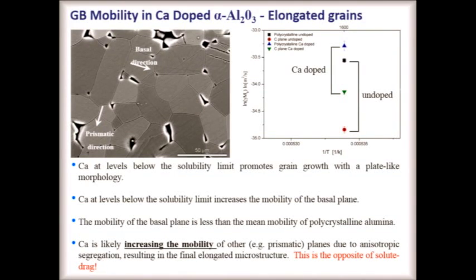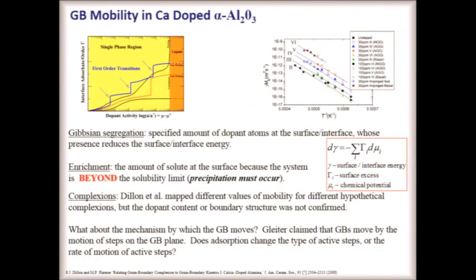And the only thing that I can imagine is that it's affecting the mechanism by which the grain boundaries move. And at the moment, the mechanism that I'm assuming, going back to Gleiter, is the motion of disconnections. So the question is, how does calcium affect either the nucleation or the kinetics of the steps that sweep parallel to the grain boundary, not the motion of the grain boundary itself? But that's an open question. The other thing is that calcium is definitely causing something exciting at the other end of these long, elongated grains, because that's where it's really going fast, and that's something that we have to look at. I can't, yes, go ahead.